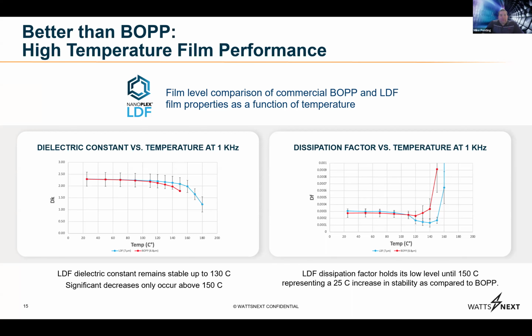Again, the LDF, the stacking of two different polymer materials together, gives you an advantage of being able to stabilize that dielectric constant with temperature in comparison to a single material. And we don't see really a drop similar to what BOPP sees until you get out to about 145C. Again, very similar loss. You have the exact same kind of film thicknesses. The only advantage is now you can run the temperature up a lot higher.